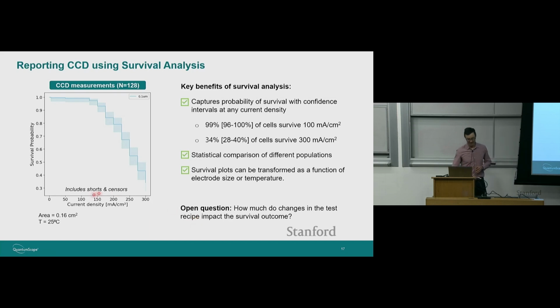So a key graph that we often look at is this survival graph, where it shows the survival probability versus the stress factor. So at low stress on the left, you have the entire population surviving. As you increase the stress you apply, you'll see the population starting to fail. And then you can generate confidence intervals. This dark line is the data, and the confidence intervals are the shaded interval around that. So we can then say with a certain degree of confidence how many cells survive a given current density. This is the point estimate here, and then these are the confidence intervals.